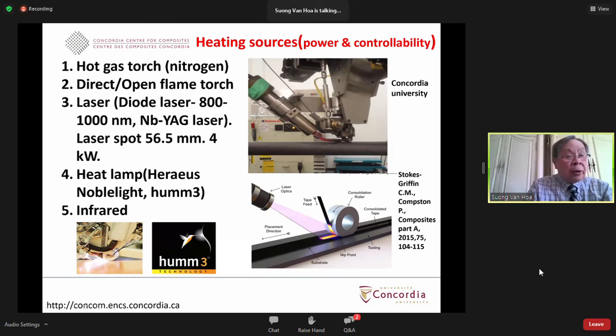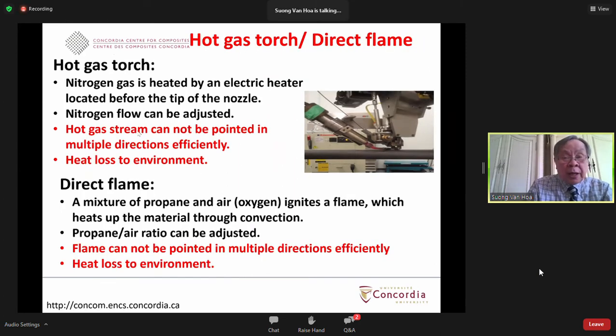So in more detail, we have the direct hot gas torch or direct flame. So here we have nitrogen gas heated by an electric heater located before the tip of the nozzle. And the nitrogen flow can be adjusted. However, the disadvantage of this is that the hot gas stream cannot be pointed in multiple directions efficiently. And also there is a heat loss to the environment. Direct flame is similar to the hot gas torch, except they use propane gas and oxygen. And also the ratio can be adjusted, but it has a similar kind of disadvantage like the hot gas torch, in that the flame cannot be pointed in multiple directions efficiently, and there is a heat loss to the environment.